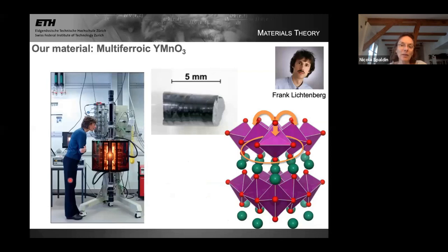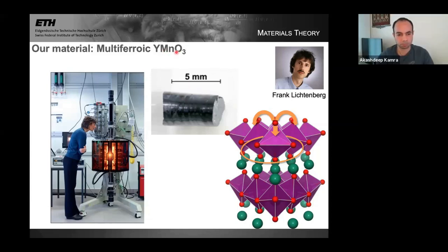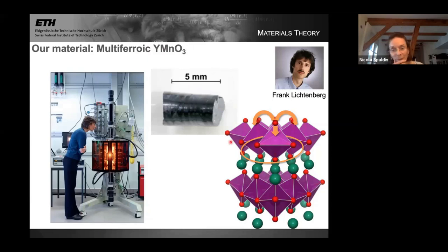And here's the material that I'm going to focus on for the rest of the talk. We'll spend some time just doing a little bit of normal materials chemistry. It's a material called yttrium manganite. It's a multiferroic material. It's simultaneously ferroelectric and actually antiferromagnetic. This is a crystal of yttrium manganite, quite a large crystal grown in our image furnace in our laboratory at the ETH by Frank Lichtenberg. So those of you who are familiar with perovskites are probably looking at this chemistry and thinking, oh, this is a perovskite structure. And in fact, yttrium manganite does exist as a perovskite structure, but this is not the perovskite structure. It has this rather exotic structure shown on the right here, which is called the hexagonal manganite structure. Not very original, it's a manganite and it's hexagonal.